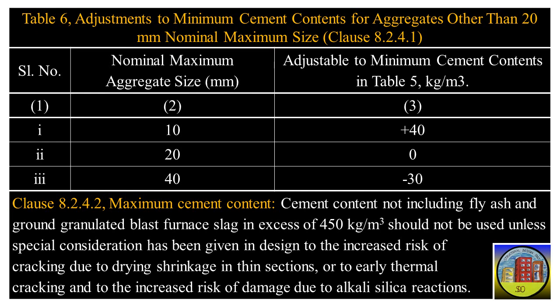Serial number 1. Nominal maximum aggregate size 10 mm, adjustable to minimum cement contents in Table 5, plus 40 kilograms per cubic meter. Serial number 2. Nominal maximum aggregate size 20 mm, adjustable to minimum cement contents in Table 5, 0 kilograms per cubic meter. Serial number 3. Nominal maximum aggregate size 40 mm, adjustable to minimum cement contents in Table 5, minus 30 kilograms per cubic meter. Now it is Clause